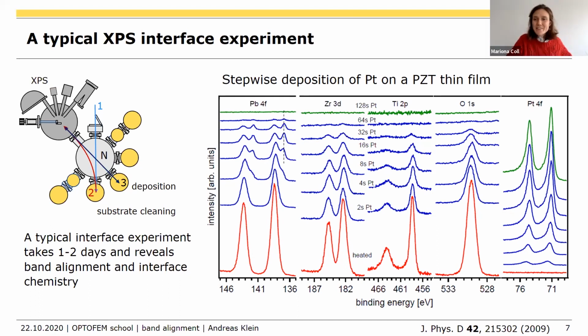Okay, good. We have another question related to this topic from Pamela Machado. She asks, how else could we easily detect oxygen vacancies? Well, from my perspective, we can look at the Fermi energy. If you change the oxygen vacancy concentration, you change the Fermi energy. And in some cases, if you have a material like strontium titanate or barium titanate, you can look at the electrical conductivity, which will depend on the oxygen vacancies. But that becomes more difficult when you go to polycrystalline materials, because the potential barriers at the grain boundaries make it more difficult to extract this.